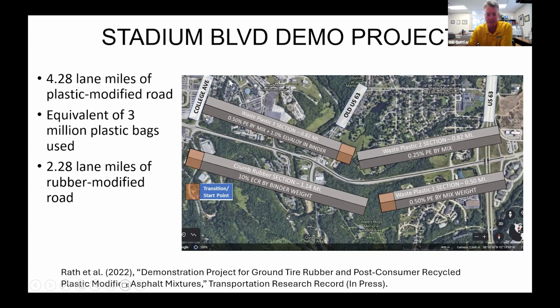And we put a rubber section in the bottom left with engineered crumb rubber, which we have a lot more experience with, probably 20 years of research and practice with that. We know it works. And then we tried 3 different plastic sections. So we did 0.5 and 0.25 PE by weight of mix, and Dow Chemical helped us identify a supplier in Texas. In Houston, it was Avangard, and I think that same material has been used up in MnROAD and NCAT as well. So we have 3 different places where this material has been used.